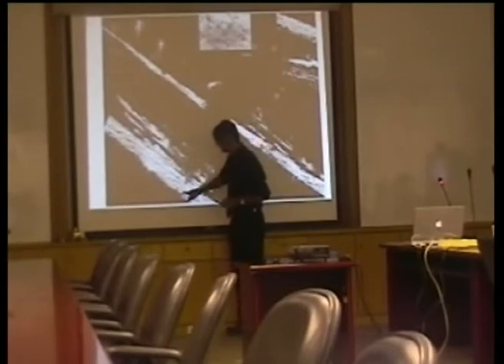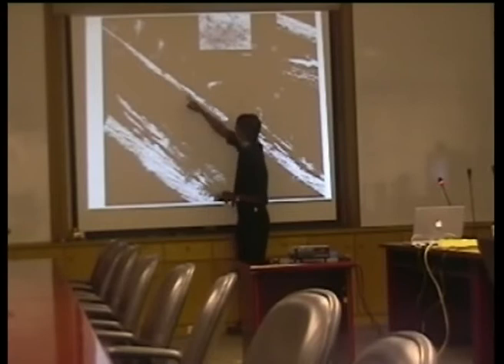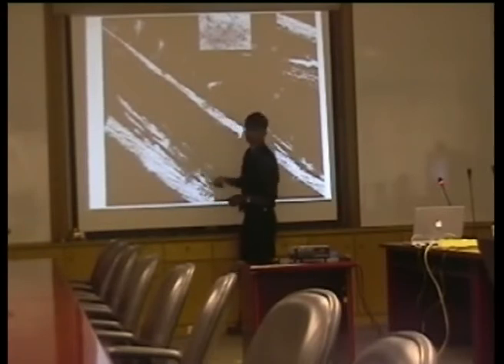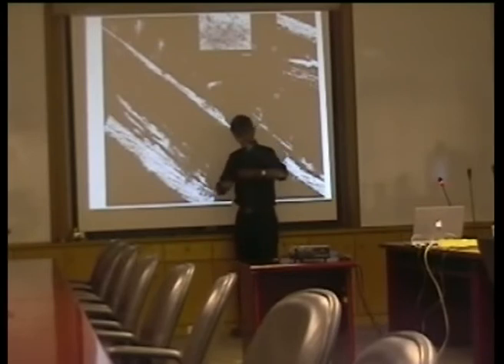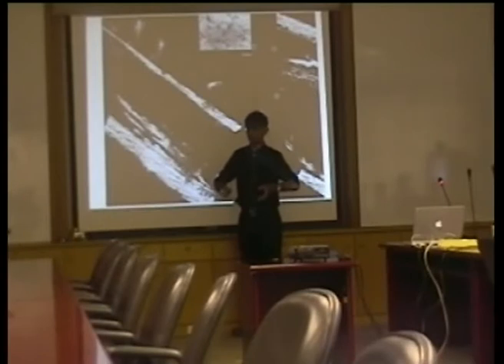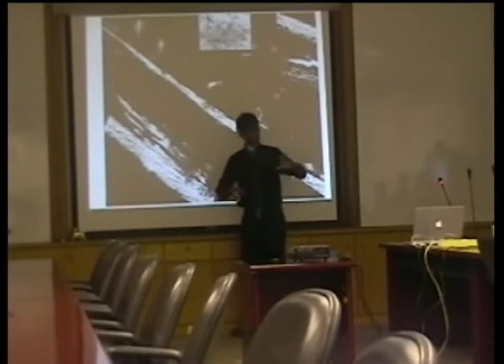Okay. If I look at the size of the small plate here, it's the same as the size of the small plate here. So what's happening is that you form a small plate, for some reason, it completely stops growing. Then you form another plate. Another plate. And if you look at them at a poor resolution, like an optical microscope, that appears to be a single plate.